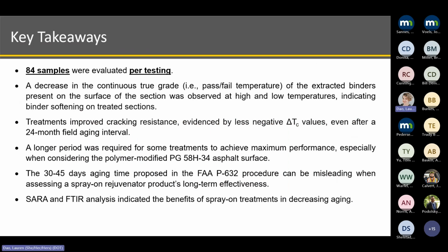Key takeaways of the study. The database that we are creating for this study is very large. You can see for each of the tests that is performed in this study, we have 84 samples being evaluated when considering the 2 surfaces, the neat binder and the polymeric binder, the 12 products applying on each of the surfaces, and the 3 field aging conditions. So the database is huge and is being used to feed an NCHRP study that is being performed right now to establish specifications for classifications and acceptance of these products.